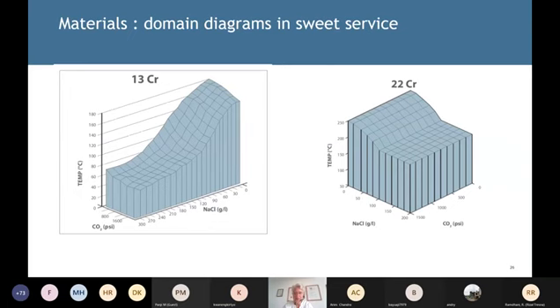So the modeling of the performance of materials, what we are aware of is that stainless steels have different levels of success in the CO2 and H2S conditions. Even in sweet conditions, materials like 22 chrome, 13 chrome materials, which are very widely and successfully used, they do have their limits related to, as you see on the left here, the chloride concentration, CO2 and temperature limits.